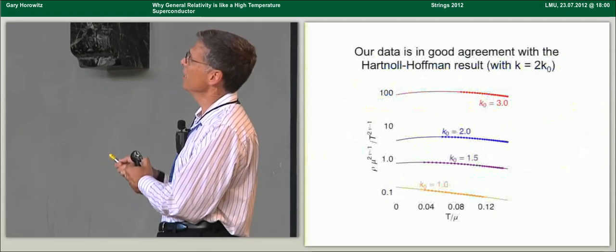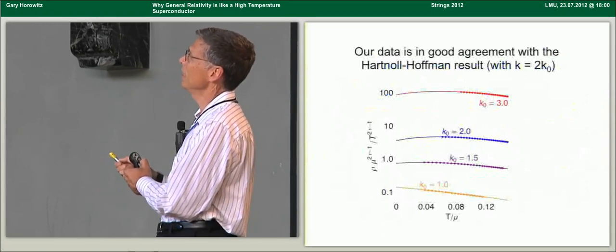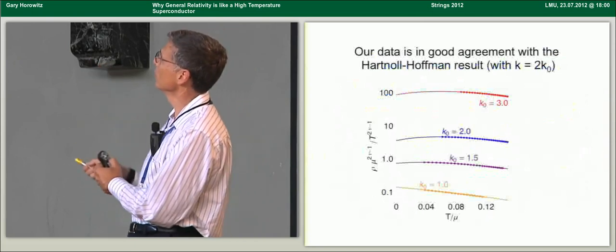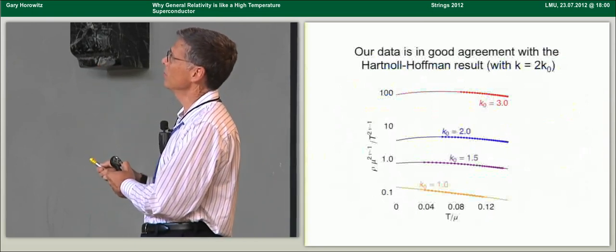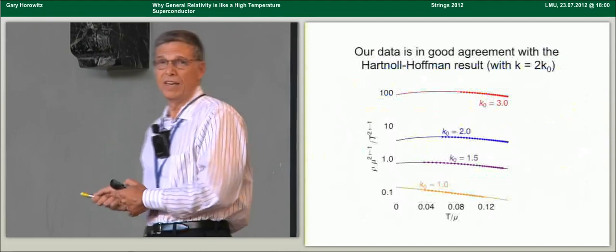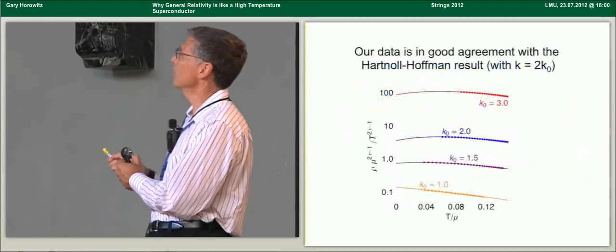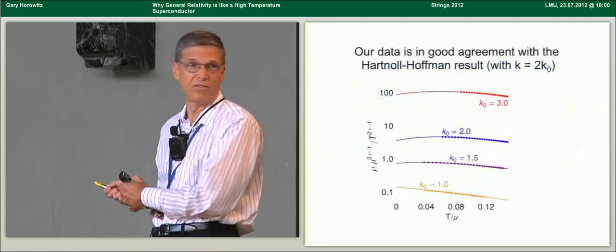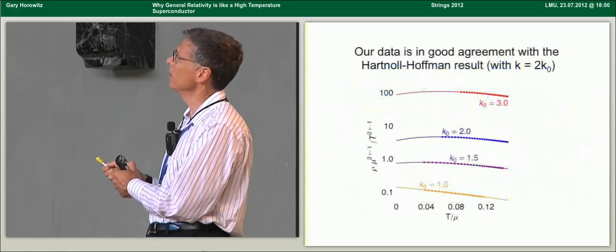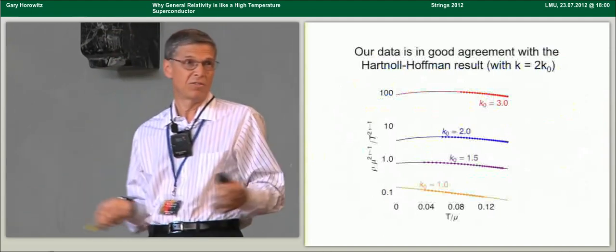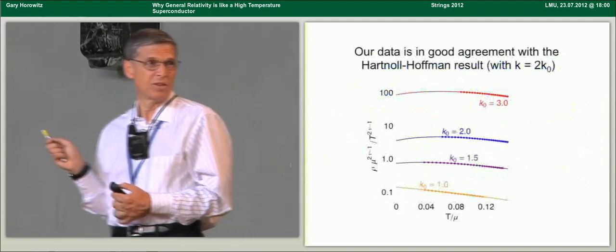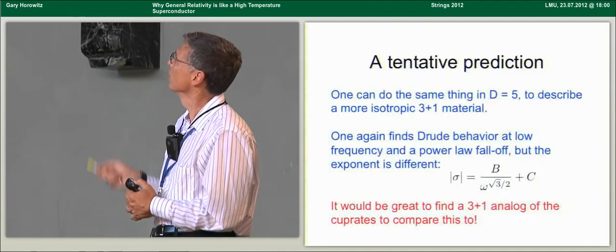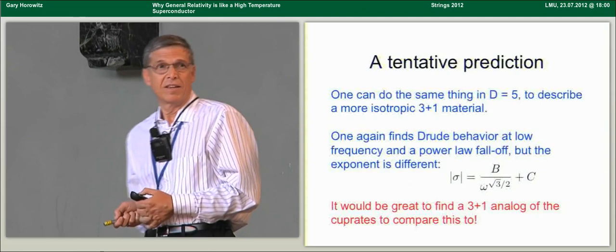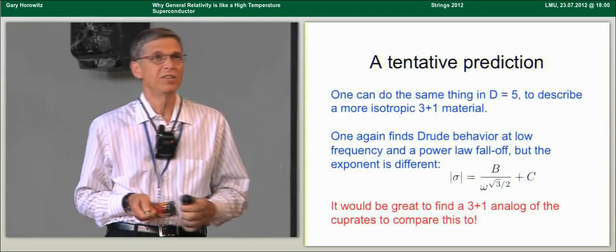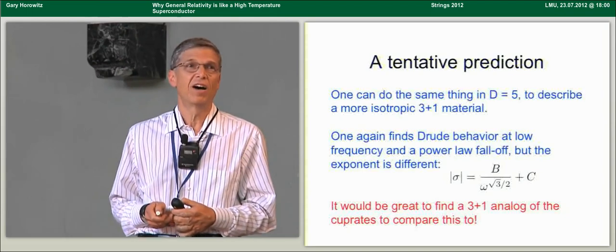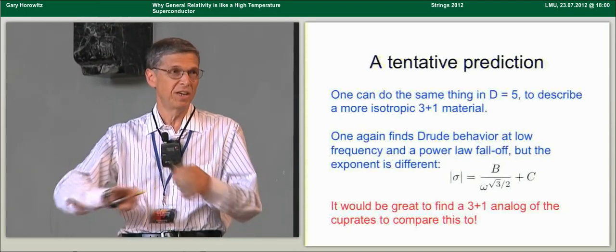So the data is indicated here, and we've done an extrapolation of the data by some like 4th order polynomial fit, and they all reach nice finite non-zero values. If our scaling had been different, these curves would be either going off to infinity or going down to 0. So the fact that they all reach nice finite non-zero values means that our data is in good agreement with this Hartnoll and Hoffman result. Okay, so now we can go further and we can say, what about AdS5? The calculation I showed you before was AdS4.